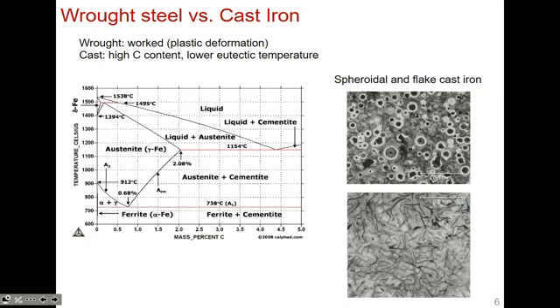Okay. Something I should also mention. Even when you have a low carbon content, so what we were talking about before was 0.77, here it's 0.68 weight percent. But whatever the eutectoid composition is, when you drop the temperature below the eutectoid temperature and then wait long enough, we said, okay, it's going to form pearlite, right? We talked about the microstructure. We talked about the phase diagram. We can compute all the phase weight fractions that we want. But then if you age it long enough, you get all the stripes, the layered microstructure. If you wait long enough and allow diffusion to happen, you actually will get some spheroidal microstructures that look like this. So not great, there is actually a penalty to pay if you age it too long. So certainly processing plays a role in enhancing mechanical properties in these systems.